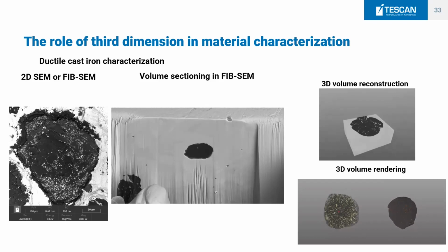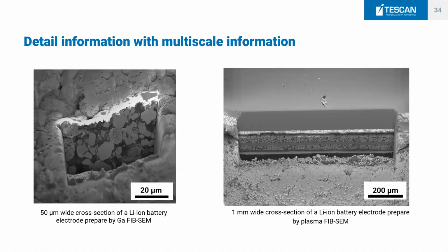You can see that this feature is as small as a couple of microns. We have two systems in our portfolio. One is gallium FIBSEM and the second one is a plasma FIBSEM, and they are both very relevant to materials science. Both of them have their own place, but for now, you could just remember that one of them is able to mill really large cross-sections in the real world scale. That's the right-hand side, the plasma FIB. So you can really mill large 1 millimeter wide cross-sections.